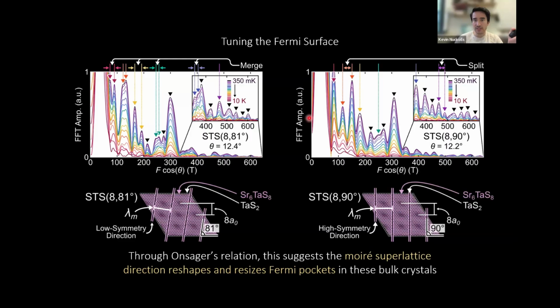Through a careful analysis, you can actually find that these Fourier transforms are clearly different, but quite comparable. And so by comparing different peaks, we can see that in many situations, most notably if you rotate the Moiré superlattice from a low symmetry direction to a high symmetry direction, many neighboring peaks appear to merge very cleanly into sharp peaks, whereas this double peak right here appeared to split very nicely in the high symmetry Moiré superlattice. So this suggests, through Onsager's relation, that the Moiré superlattice in these compounds is reshaping and resizing the Fermi pockets of bulk crystals, as programmed through their chemical synthesis conditions.